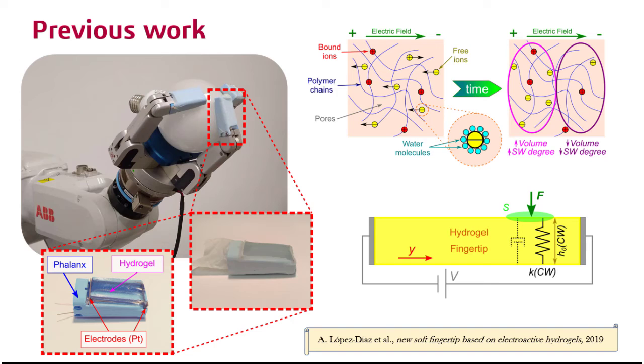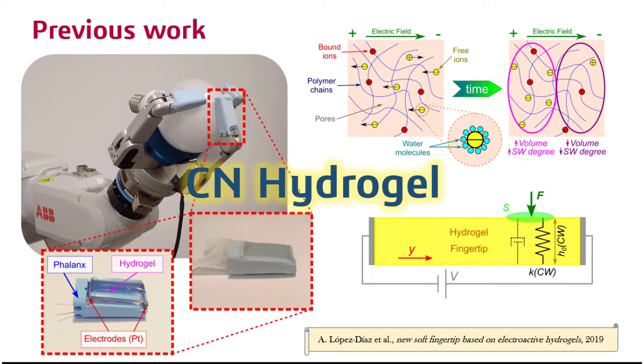Prior to this work for RoboSoft 2020, we developed a hydrogel-based soft fingertip capable of changing its stiffness and volume under an electric field. We called this material CN hydrogel, as it is based on a cationic network with free negative ions that drag water when an electric field is applied, originating a gradient in the swelling degree that causes the changes in stiffness and volume.